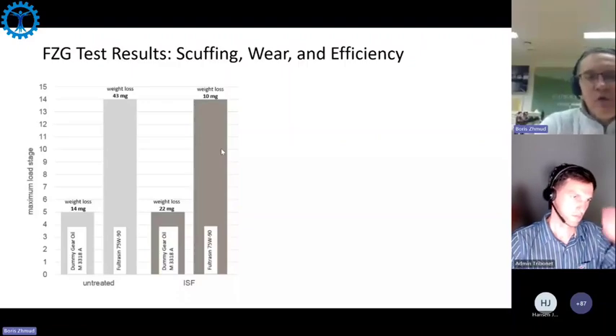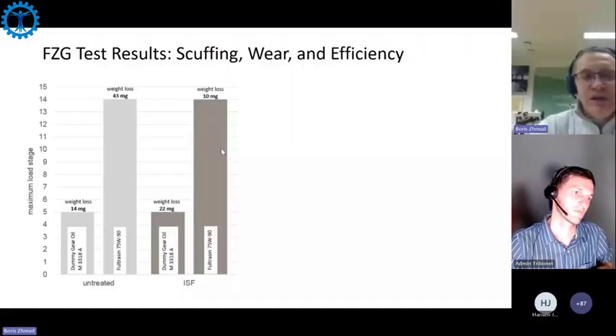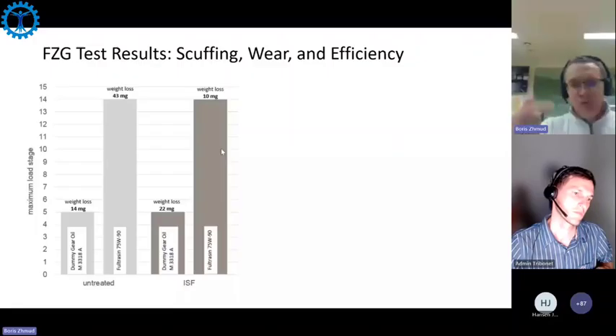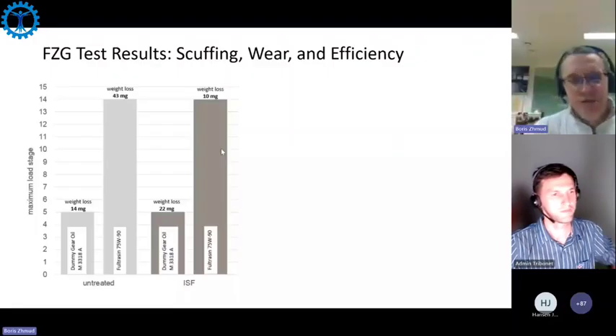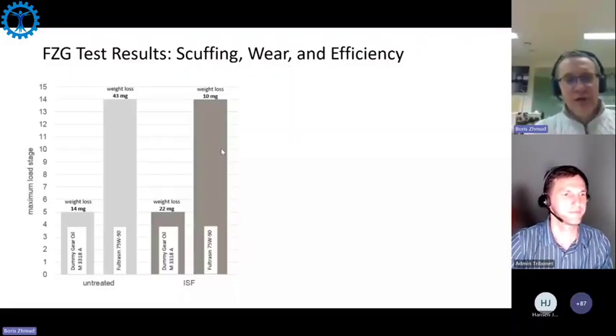You will see that the low pillars refer to additive-free oil. It has no sulfur whatsoever. So the additive-free oil will fail at the same load stage. It will fail at load stage 5, no matter whether you have ground gears or mechano-chemically finished gears. They all fail at stage 5. For the fully additivated GL-5 oil, they all will pass stage 14 without failure.